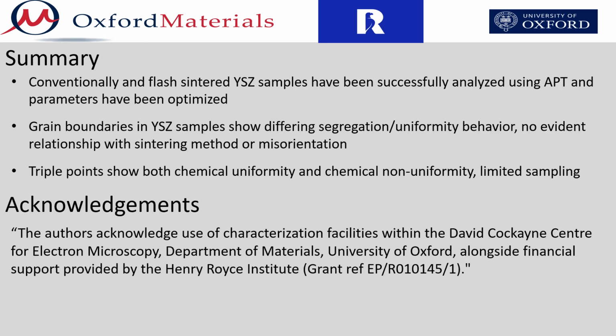In conclusion, atom probe tomography has been successfully applied to both conventionally sintered and flash-sintered yttrium stabilized zirconia samples. Grain boundaries have shown variation in chemical segregation and uniformity, however no clear relationship can be discerned between flash-sintered and conventionally sintered specimens. Finally, triple points show both chemical uniformity and non-uniformity, however due to limited sampling, no relationship with sintering type can be drawn.